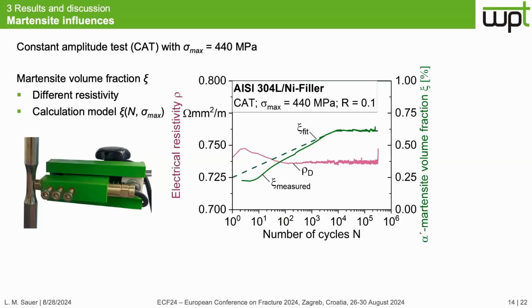And at last, the influence of martensite transformation on the electrical resistance was compensated. It is necessary because the used metastable austenite shows martensite transformation because of the stress. And martensite has a different electrical resistivity than austenite. So the martensite volume fraction during the fatigue test was measured by using a ferrite scope.